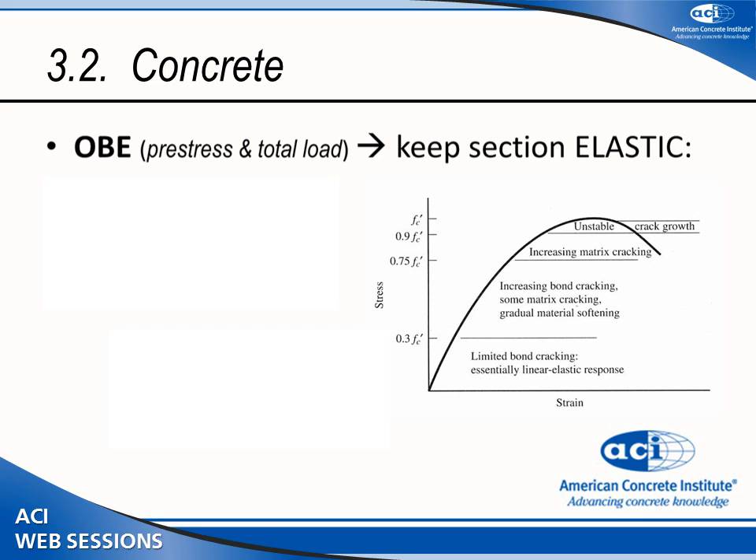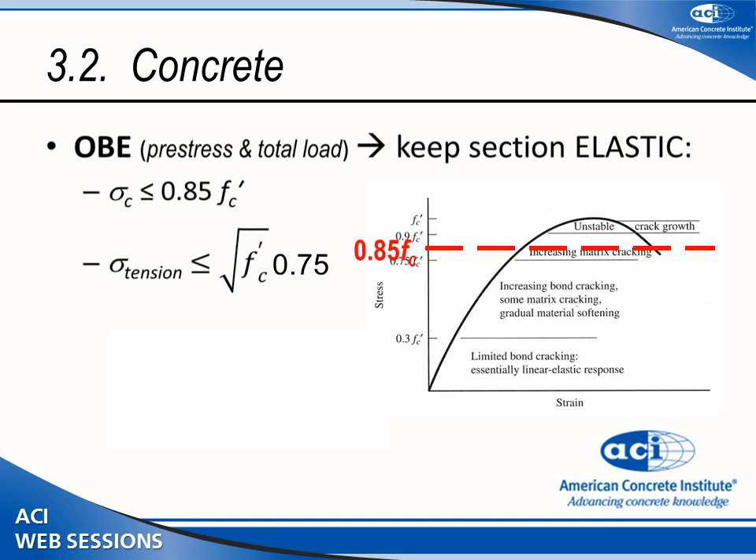Further, under operating and seismic conditions the walls of the tank exhibit elastic-type behavior, and in that case under prestress with total losses we want to increase the effective prestress. The reason is that non-cracked concrete in compression is the main thing helping you maintain liquid tightness. If one face cracks, it will eventually open on the next cycle, so you must protect the compression to keep the liquid in. Practically, you want to keep your compression stress less than 0.85 of f c prime.